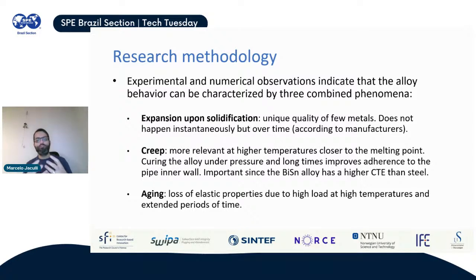So then it's going to lose its properties, and therefore it's going to decrease its sealing capability. So it's something that also needs to be investigated. There is some data you can find on this, but not completely. But it's an important effect that you have to take into consideration, especially since this plug is going to be there for a very long time. So you need to take into account the degradation of this particular material.